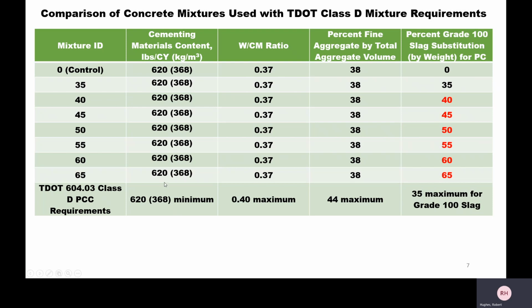And here we see some of the TDOT requirements. This is the minimum that I was speaking of a minute ago, 620 pounds per cubic yard. Now, for our water cement ratio, we use what we found to be an optimum ratio of 0.37. We keep that a little less than the 0.4 max that TDOT requires. Same thing with percent fine aggregate by total aggregate volume, which is 38, a little lower than the 44 max, but we have discovered that it is a pretty optimal percent for us. And like I said earlier, anything above a 35% slag substitution for Class D concrete is out of spec, so we have six batches that are out of spec for TDOT to examine how we could go beyond it.